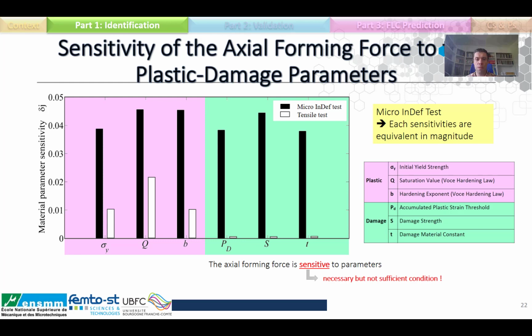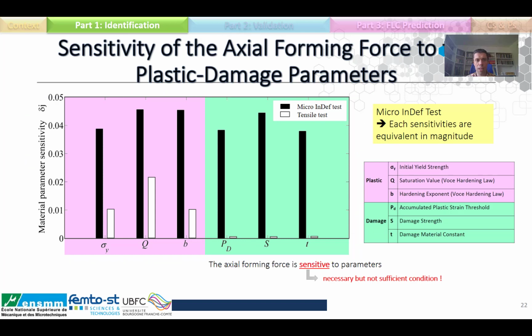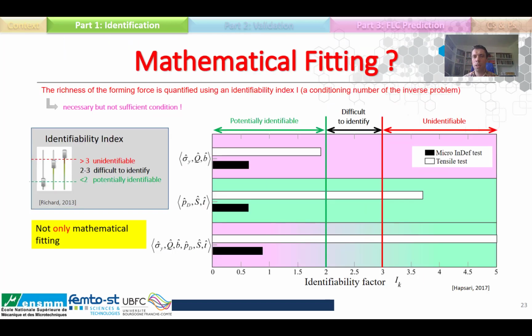Therefore, we performed a sensitivity study on parameters from the Lemaitre model. The graphic shows that the Micro InDef test is equivalently sensitive to all parameters. As you can see here, all the black graphs have the same height, while tensile force is sensitive to plastic and elastic parameters, but is not very sensitive to damage and fracture parameters. Moreover, the sensitivity of tensile force is lower for overall parameters. Knowing that axial force is sensitive to parameters is necessary, but it's not a sufficient condition for parameter identification. The information richness contained in the forming force should be quantified with an identifiability index.